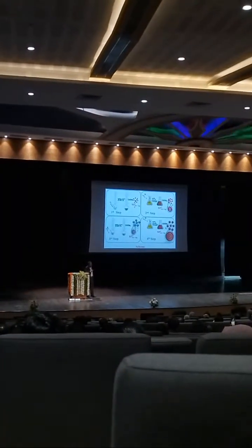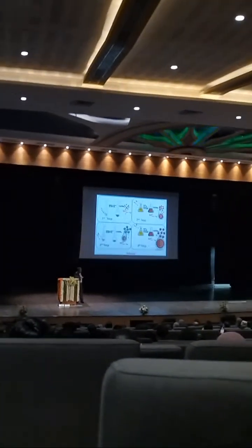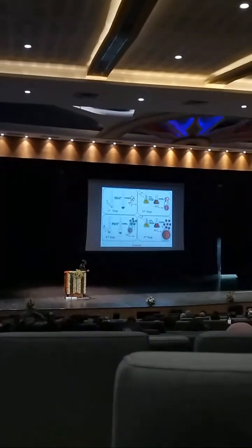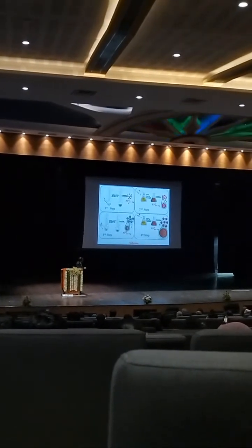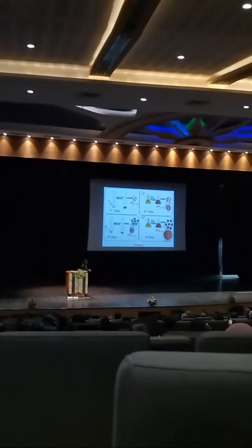Okay, so we use the seed to grow the silver layer outside of this. Now here the thing is that silver generally we cannot reduce by ascorbic acid. So to reduce the activation energy, we use the heating method. Okay, so a nice smooth surface of silver comes out. Again we use this as the seed to grow an outer layer of gold.